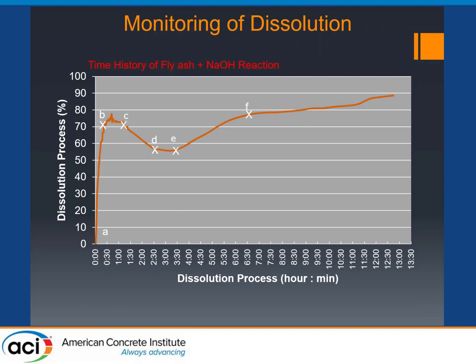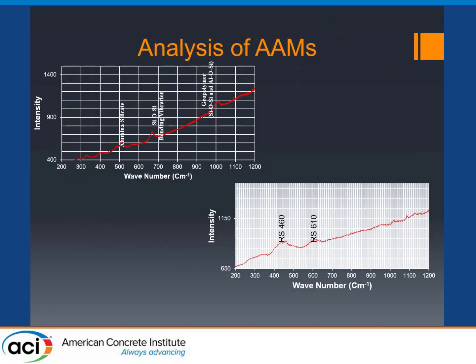So here shows dissolution process versus dissolution time. It kind of reminds me of the classic hydration process of C3S. What we see here is competing effect of dissolution, which we see increase in concentration. And then when ion saturated, we have the geopolymer generated. But in this case, we have more sodium hydroxide. Then if you dissolve this geopolymer, we have a lower dissolution percent. Just to show you an example of this monitoring dissolution process.